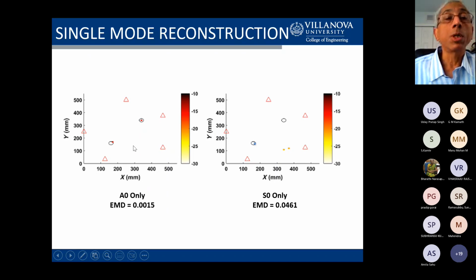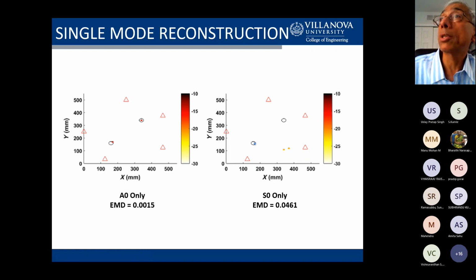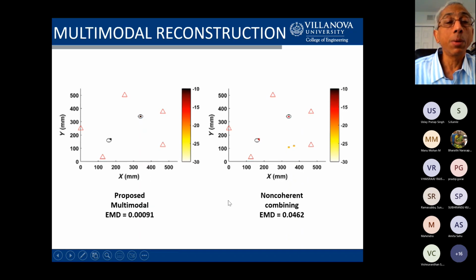So again, quickly, if you have two defects in your structure, the open circles here represent the locations of the defects, the triangles represent the location of the transducers, and the solid colored small squares that you see represent our predictions of where the defects are based on sparse reconstruction. You can see over here, if you used only the A0 mode for sensing these defects, then you can identify one defect well, but not the other one. And if you use the S0 only, then you can identify one defect, but not the other one. You can see where the guesses are way off from where the defect is. On the other hand, if you simultaneously use both modes, what we call multimodal imaging, you can identify where both defects are fairly precisely. So that's the advantage of multimodal. And this, by the way, is an experimental study and not a theoretical one.